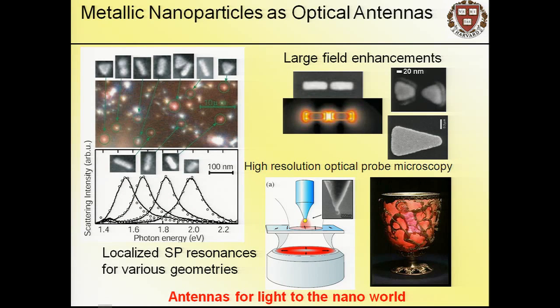Metallic nanoparticles act as optical antennas. The plasma resonance depends on shape and type of metal. We can make these by lithographic means—typically resonant optical antennas. Light polarized along this direction gives rise to charge oscillations with size-dependent resonance. At resonance, you can create very intense fields in the gap. Optical antennas go back a long time.